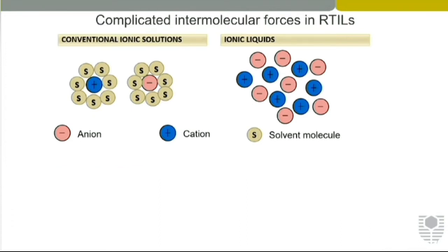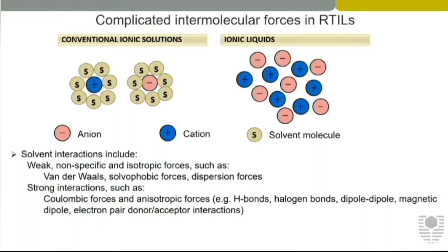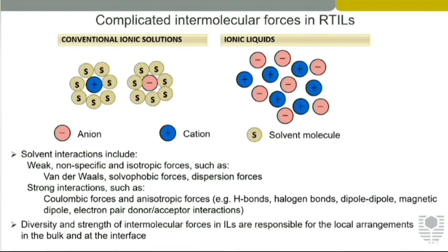So the interactions between the ions here are much different to conventional ionic solutions. And ionic liquids can be very complicated because they have lots of solvent interactions, including some of these weak non-specific forces like van der Waals, solvophobic and dispersion forces, and some stronger interactions including coulombic and anisotropic forces, particularly the hydrogen bonds. When you change the structure as well, you can get some strong hydrogen bonding, and dipole-dipole electron pair donor interactions. So much more complicated than traditional solutions.